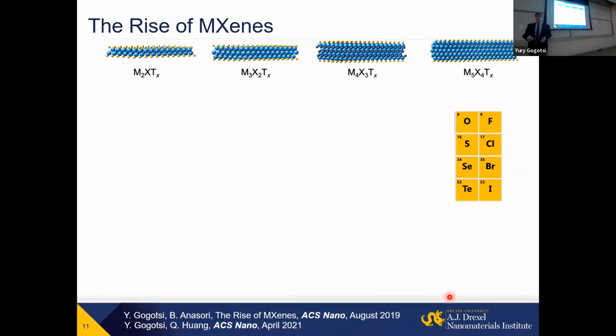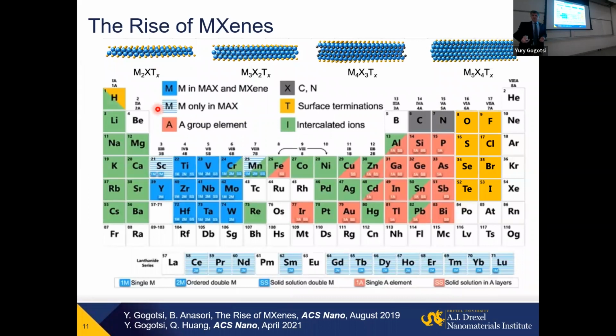Now, what do we have? We have these 4 structures possible so far, from M2X to M5X4. We have these transition metals, and you can add, of course, all rare earth metals to those. You can have carbon and nitrogen. You have at least 10 surface terminations: oxygen, chalcogens, or halogens, hydroxyl groups, amino groups on the surface here. And you can also intercalate a variety of other elements between the layers. So pretty much we can have access to designing using the entire periodic table, the majority of elements. Some that are not there probably still have not been put there.